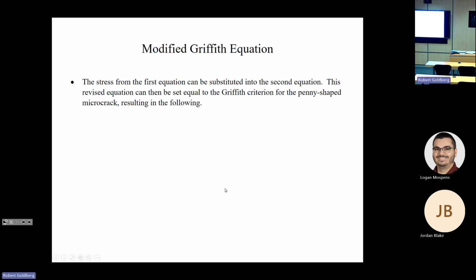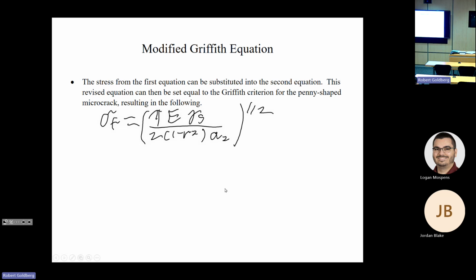So what we can do then is, for the little crack, the penny-shaped crack, the failure stress, the stress that will result in failure of the little crack, the mini crack, because it's a penny-shaped crack, is equal to pi times the modulus times the surface energy divided by 2 times 1 minus the Poisson ratio squared multiplied by A2, all this to the 1/2 power, and this A2 now is the half crack length of that mini crack, that little crack that's right at the tip of the big crack.